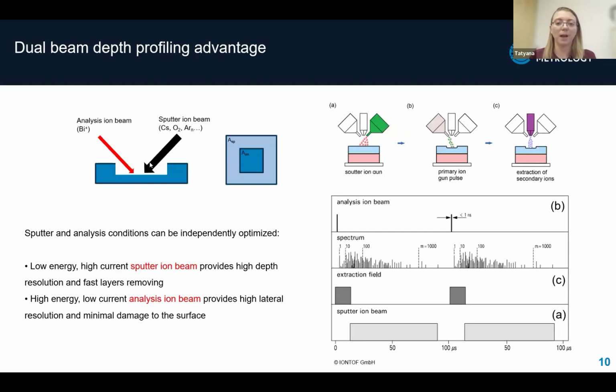The sputter beam operates at low energy but high current, which allows it to efficiently remove layers of the sample material while maintaining good depth resolution. Meanwhile, the analysis beam uses high energy but low current, which provides excellent lateral resolution for analyzing the surface with minimum damage to the sample. It is common to use a sputter crater three times larger than the analysis area to avoid measuring the edges.